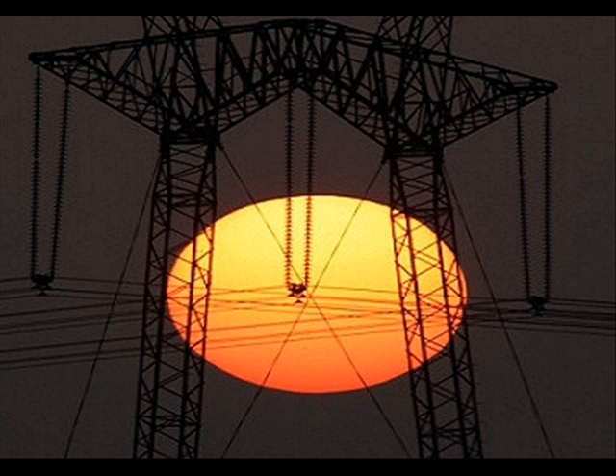And in the early application, in the early study of these solar panels, how much power were they able to generate? How much of the total energy picture would this contribute to? Oh, that's a very good question. Let me give you an example. A typical silicon solar panel on the rooftop is about 16%. 18% is probably already high-end. In our laboratory, we produce the transparent solar cell at about 4% so far, but we have a plan to reach about 10% efficiency in the next 5 years.